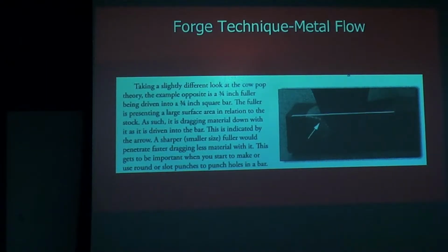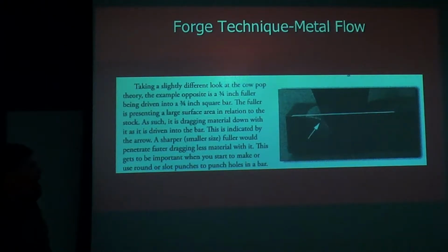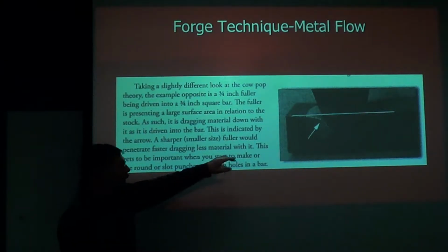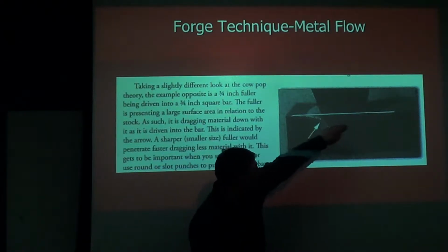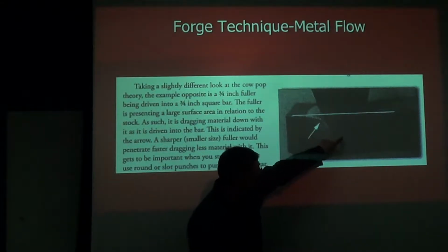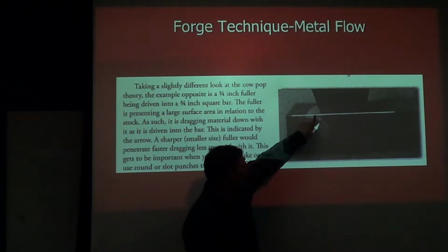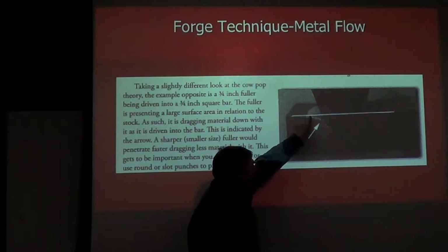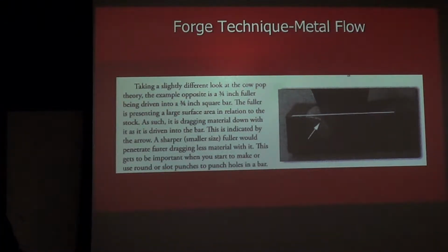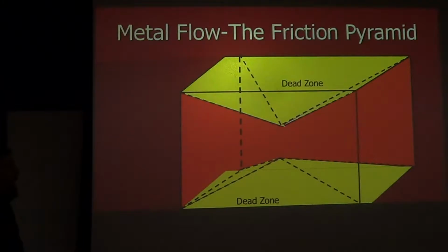Here's another example of that. This is showing a tool being used to create an indentation, but what we can see is that this piece started off as a nice flat, and we drove the tool in, but the metal is not in contact with the tool along its entire profile. It actually is separated here. We've got this metal being pulled down this way. Right? What's happening is there's friction between, in this case, that shaped tool, or between the flat tools that we use at work. And I'll show that in this way.